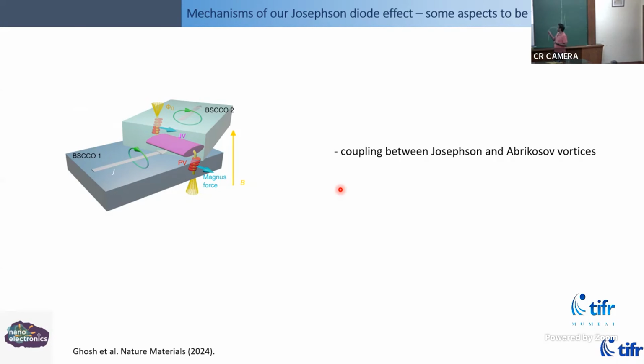And there are still some loose ends, which I'm happy to talk more about. So what happens in these kind of high temperature superconductors, there are two kinds of vortices. When you apply a perpendicular magnetic field, you get vortices which are the Abrikosov vortices that we know, and another vortex which is called the Josephson vortex. That's because these high temperature superconductors have these copper oxide planes. Anytime the phase between two copper oxide planes moves, you have a motion of a Josephson vortex.